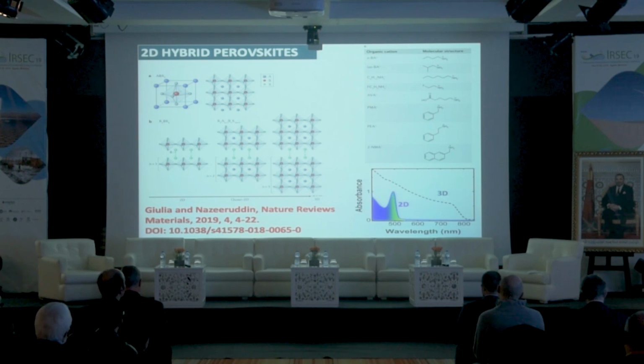In our lab, we are trying to combine the beautiful properties of low dimensional perovskites. So let me come back to what a low dimensional perovskite is. If you take our normal perovskite, that is n equals infinity, where the cation fits into the cavity according to the Goldschmidt tolerance factor. This forms a 3-dimensional perovskite. Now, if the A cation is bigger than the organic cations I mentioned, methylammonium, formamidinium or cesium, then you slice into low dimensional perovskites, which can be a single sheet, or 2 sheets, or 3 sheets, by using this type of cations.